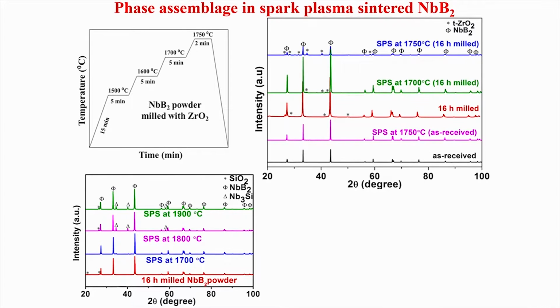And since it is a porous ceramic powder, there are a lot of void spaces. Now, when current is trying to pass through these powder particles, if the powder particles are non-conducting, the majority of the current will pass through the graphite die wall. But some current will also pass through the powder compact, and because of the voids the current will experience resistance, and because of this resistive heating and Joule heating, the temperature locally will shoot very high, leading to higher mass transport. That is the entire mechanism of spark plasma sintering of ceramics.